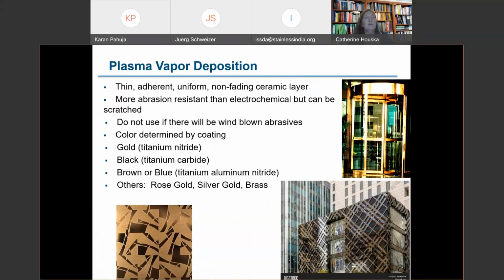Plasma vapor deposition has become increasingly popular. It's the application of a thin adherent ceramic layer to the surface. The color is determined by the ceramic that is applied. So gold is titanium nitride, black is titanium carbide. There you can obtain blues and browns and a whole range of different colors. There are quite a few projects out there where stainless steel is being used instead of copper alloys, because you don't have to worry about color change and maintaining a coating on a copper alloy to retain the color.